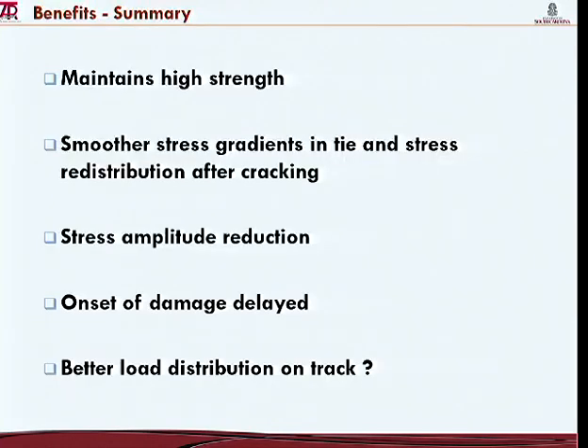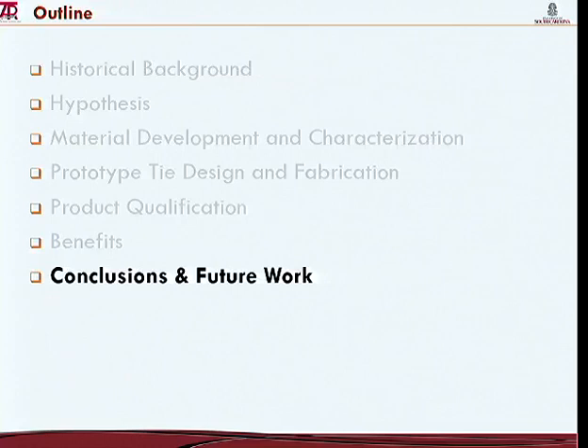So benefits, in summary. The new material maintains high strength, with smoother stress gradients in the tie and stress redistribution. Stress redistribution takes place after cracking. Amplitudes of stresses are reduced. Onset of damage is delayed, meaning higher load to see the first cracking. And the next thing that we're looking at is better load distribution on the track because it's more flexible. So the hypothesis here again is that we're going to see a better distribution of the load on the track. So conclusions and some future work.